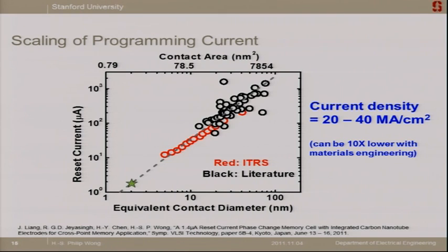The black circles are the data from the literature, and the red circles are the wishful thinking from the ITRS. And you can see that, of course, because it depends on area, there's a straight line down here. The current density required is anywhere from 20 to 40 megaamps per centimeter squared. So not milliamps, megaamps per centimeter squared. And doing materials and engineering sometimes could allow you to have another 10x lower current density. So that sets the energy dissipation.